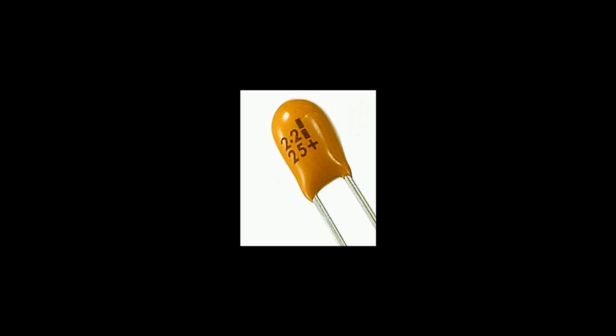The field crystallization followed by a dielectric breakdown is characterized by a sudden rise in leakage current within a few milliseconds, from nanoamp magnitude to amp magnitude in low impedance circuits. Increasing current flow can accelerate in an avalanche effect, and rapidly spread through the metal oxide. This can result in various degrees of destruction, from rather small burned areas on the oxide to zigzag burn streaks covering large areas of the pellet to complete oxidation of the metal. If the current source is unlimited, a field crystallization may cause a capacitor short circuit. In this circumstance, the failure can be catastrophic if there is nothing to limit the available current, as the series resistance of the capacitor can become very low.